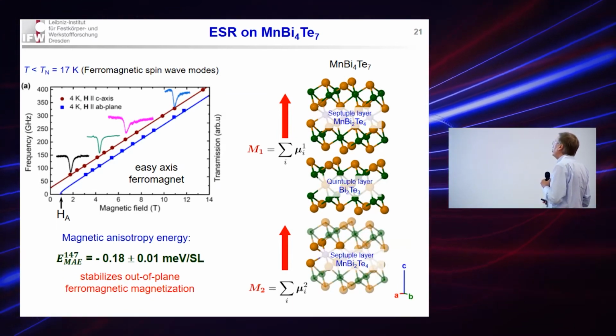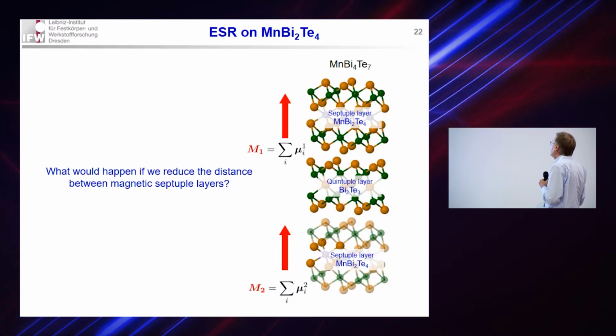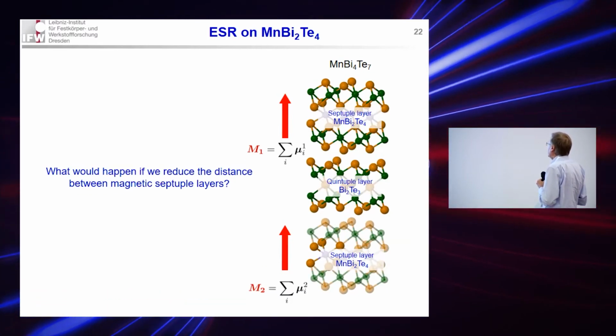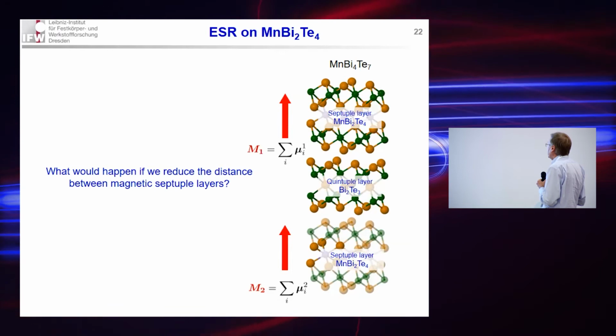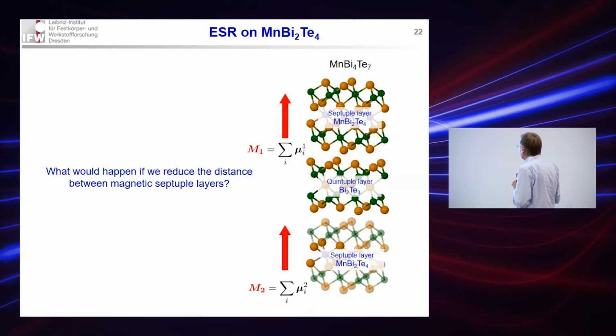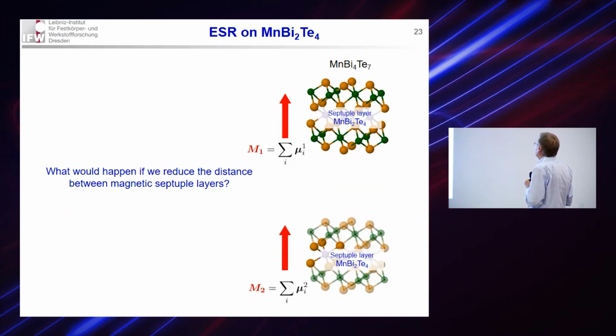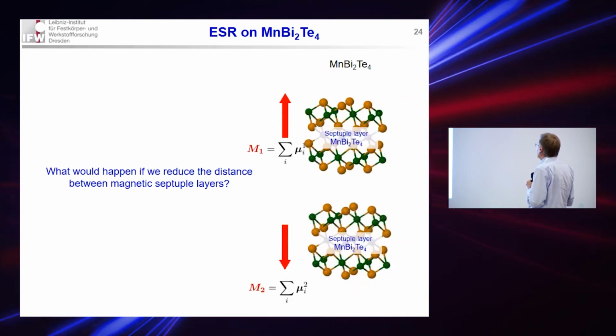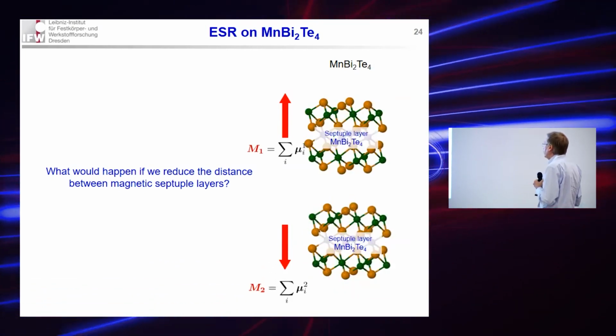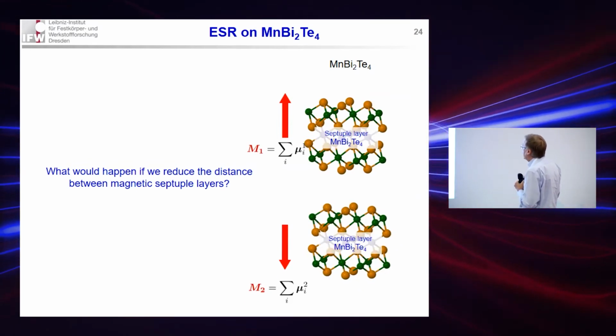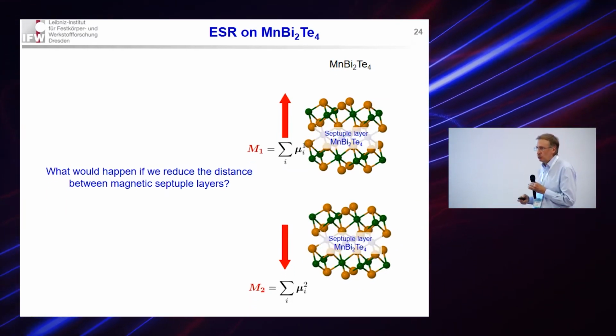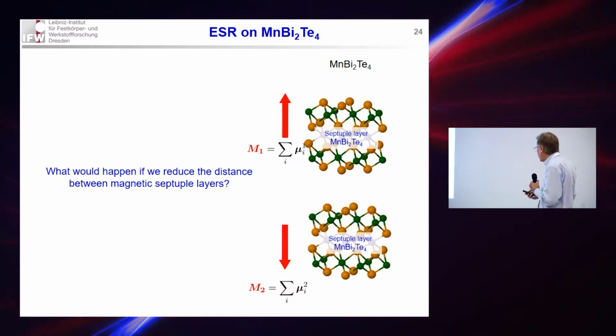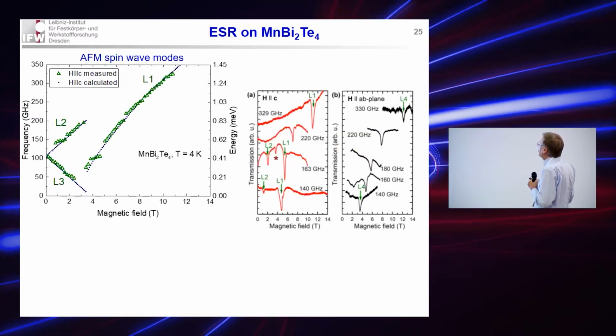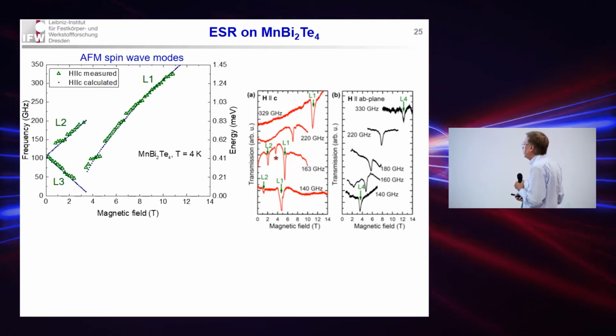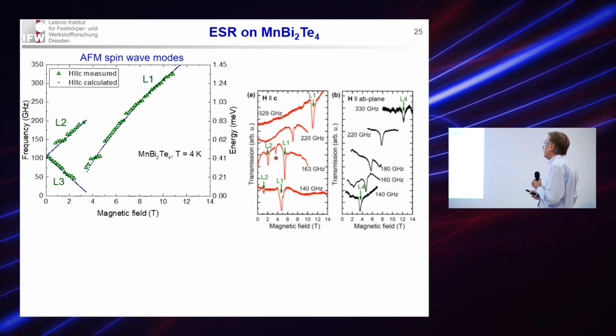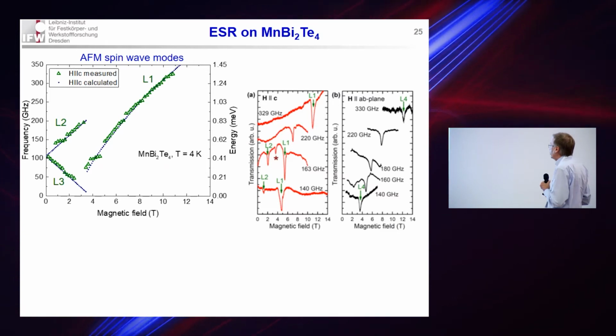But the next question: what happens if we just reduce the distance between these two magnetic layers? For that, we can simply take out this quintuple layer, which is non-magnetic, and then, of course, the distance between these magnetic layers would be shorter, and the antiferromagnetic interaction between the sublattices would be expected to be stronger. And indeed, in this material 1-2-4, which doesn't contain non-magnetic units, we find an entirely different excitation spectrum in the magnetic ordered state.